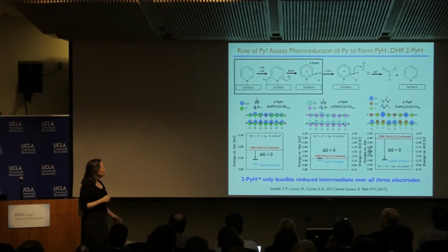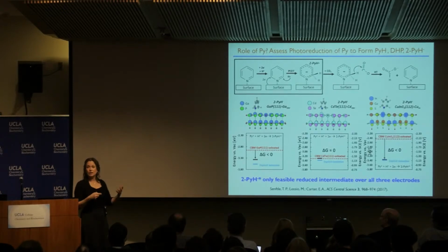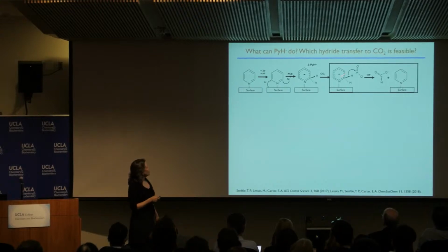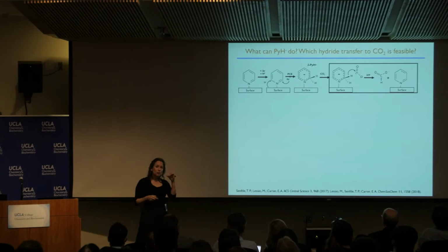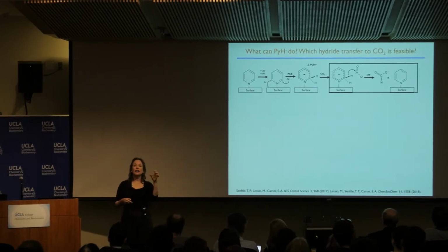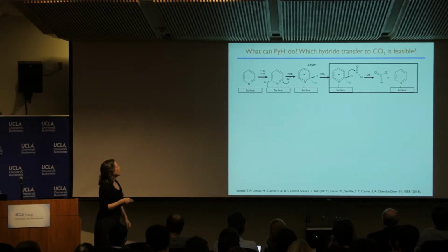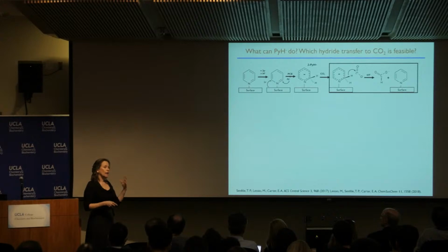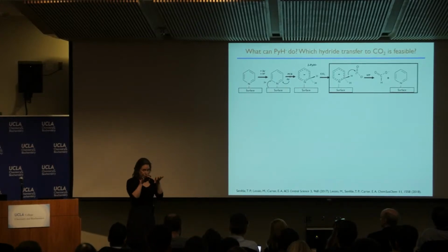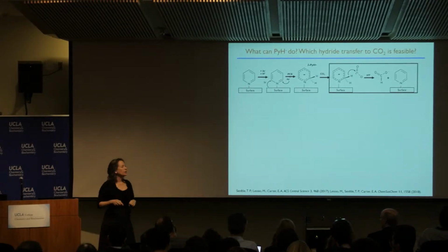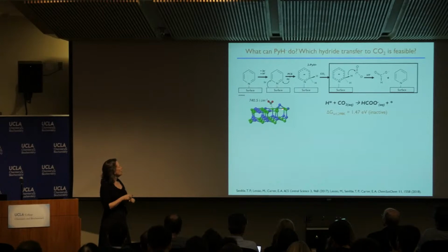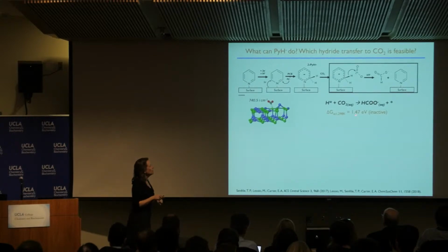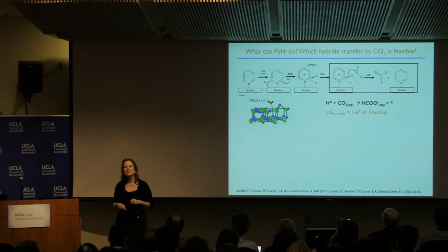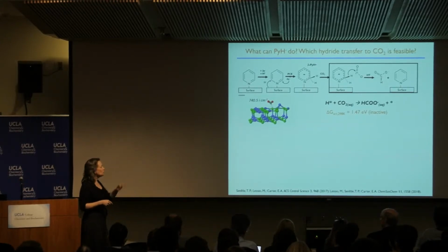And so then we went on from there and said, okay, so you can make this. Is it a bystander, or can it do the chemistry? So we wanted to check, if you make 2-pyridinide, which is essentially adding a hydride to pyridine, can that then deliver a hydride to carbon dioxide to make formate? We wanted to compare it to what happens with the hydrogen on the surface from heterolytic dissociation of water. So could it be that hydrogen dissociates directly from the phosphorus and goes to CO2 and makes formate? Well, that turns out to have a very high barrier, about 3 times the level at which we think is acceptable for this chemistry to be happening. So we don't think that's happening at all. That hydrogen, once it's on the surface, is stuck.